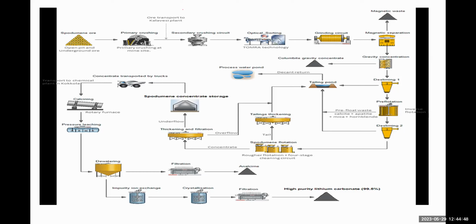So you can see that we are wasting most of our ores in Nigeria, because the Chinese man will tell you that if it's not up to 3%, it's not buying. If it's not up to 5%, it's not buying. But you can see that from 5%, we're able to concentrate it to 6 to 7%. So we can actually start this beneficiation plant in Nigeria. We can do it individually, we can get funds, we can get loans, we can start it.